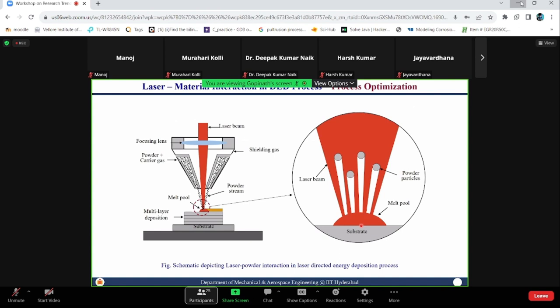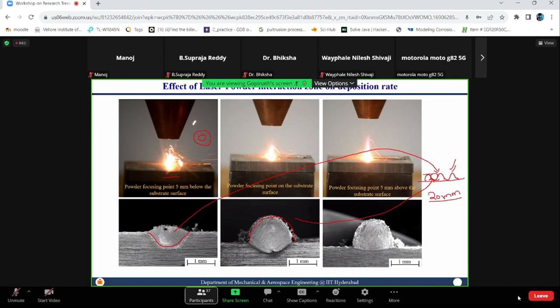Participants: Sir, should we be varying the standoff distance while laying? Yes, while depositing, once you observe too much waviness, what I am suggesting is you understand what your valley distance is from the peak, and you set the standoff distance in such a way that 20 mm is set with respect to the valley, and with respect to the peak, it will be less than 20. It can be 19, 18, 15, 14 and so on. Then that means the laser beam has to be oscillatory, moving up and down? No, no, the nozzle will move up and down. That's okay, only the nozzle.